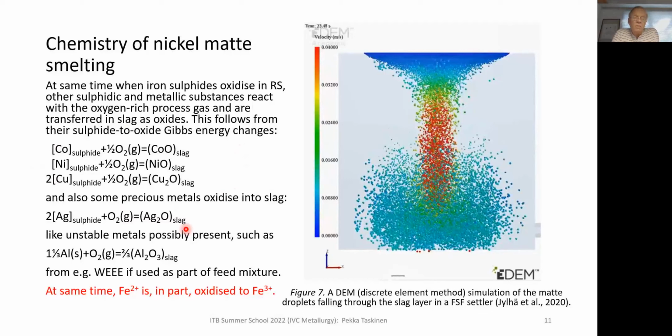So if this is true, and we have verified it in many ways and in several separate studies, that proves that the oxidation is the mechanism for the minority components to dissolve from sulfide matte into the smelting slag.